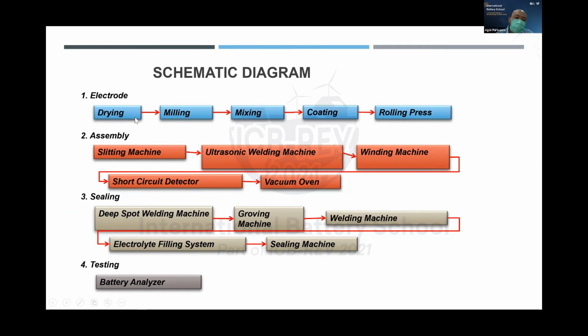We use drying. The use of drying is to minimize the water content in the active material of the battery. Then to make a good size distribution of the material, we use milling and then a mixing process to mix all ingredients or all chemicals which are used in the cathode or in the anode material, and then we coat the slurry and then use a rolling press to reduce the thickness of the electrode.